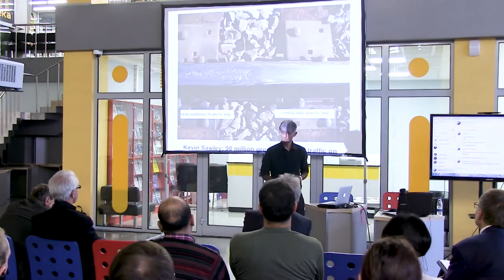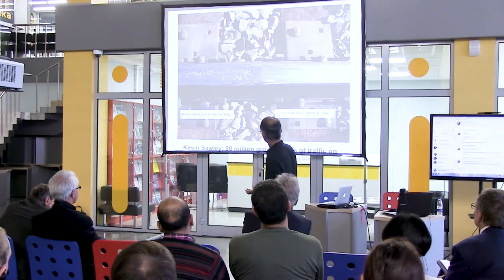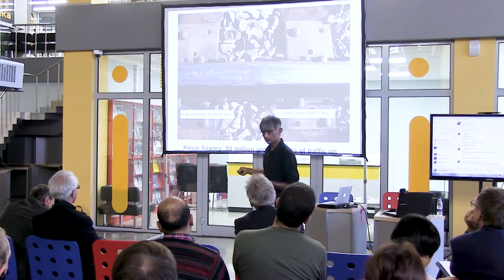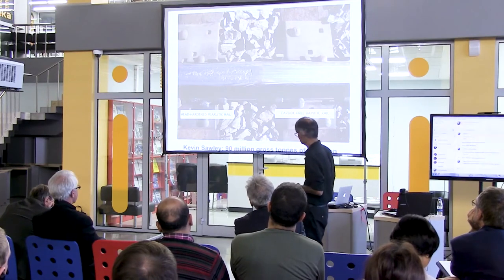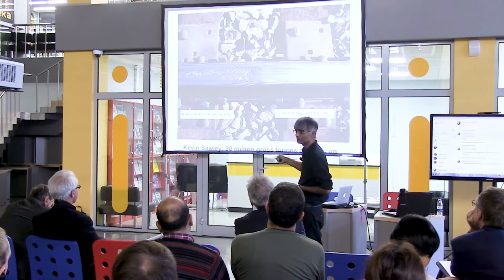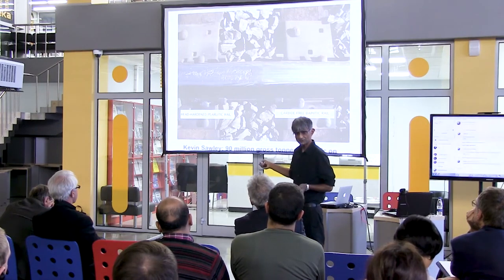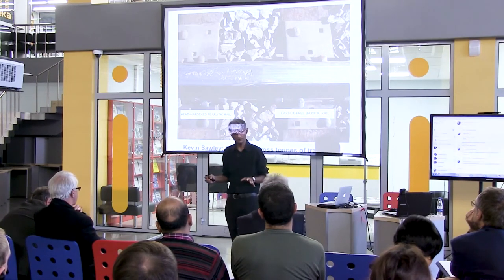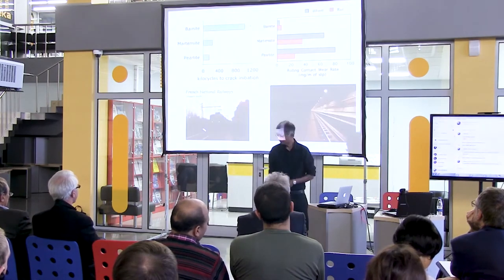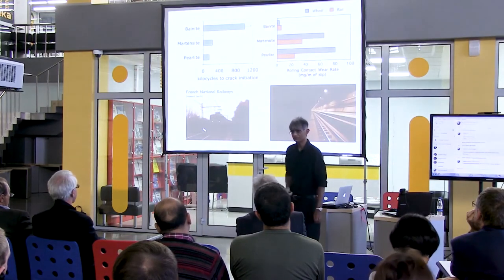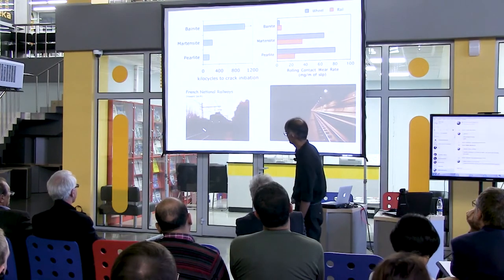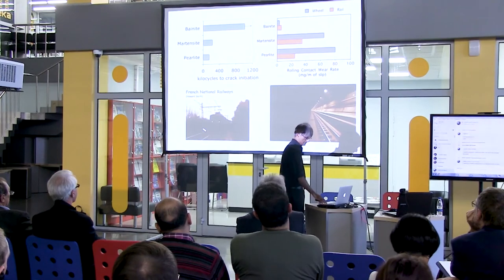This is a rail made from that material. This is ordinary pearlitic rail, which is head-hardened — good quality pearlitic rail — and it has had 90 million tons of traffic on it. You can see the difference. This material is also in the channel tunnel between the UK and France. These are the carbide-free bainitic rails, which have very, very good rolling contact resistance and wear resistance.